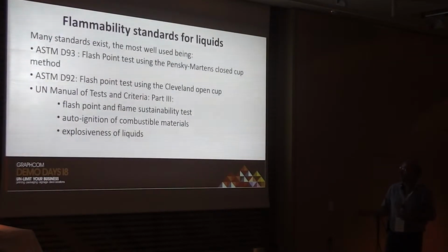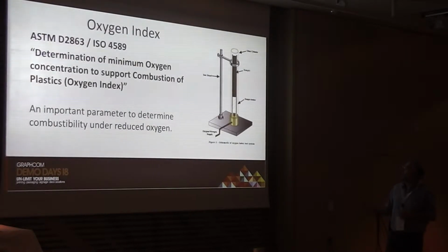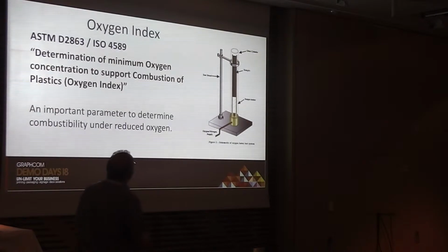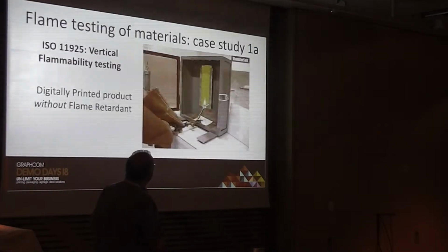And there's more liquids. Okay, I'm not going to go through this. There are different tests we carry out. For example, there's another one called the oxygen index. Let me come this way before I get a stiff neck. The oxygen index, that's how much oxygen is the minimum enough to cause combustion of this material. We have a glass tube, this is a sketch, and we actually change the ratio between nitrogen and oxygen until we get the beginning of combustion. That's quite important because in a closed area, if there's a draft, you might want to reduce your draft to make sure that the oxygen reduces very quickly so the fire will go out. Okay, there's some case studies quickly, if I can get it down there.